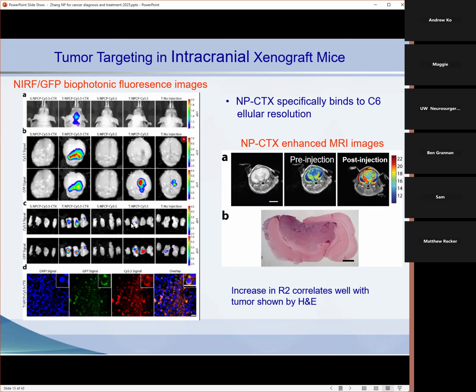For example, the left shows the fluorescence-labeled chlorotoxin nanoparticle, and this row shows the GFP-expressing brain tumors. We can see that the fluorescence of the nanoparticle co-localizes with the brain tumors. Then we sectioned the brain tumor and looked under the microscope, and the nanoparticles also co-localize well with the GFP-expressing tumors. And here's the MR imaging. This is pre-injection of the nanoparticle. We don't see anything, and there's very little contrast. After injecting the nanoparticle for 48 hours, the MR imaging showed that the nanoparticle increased the contrast in the tumor regions, which was confirmed by HE staining.